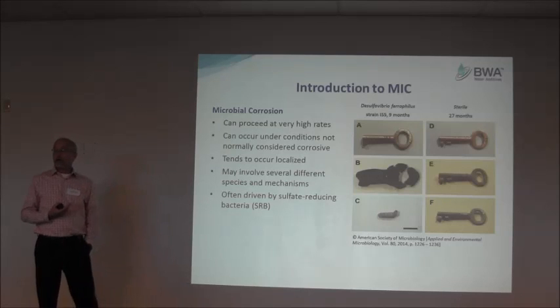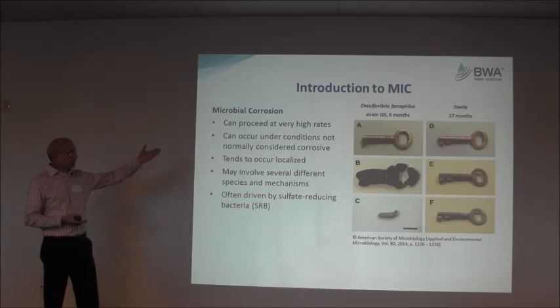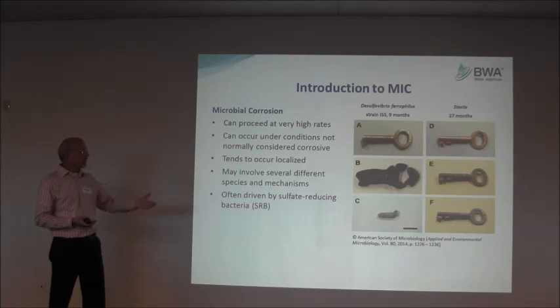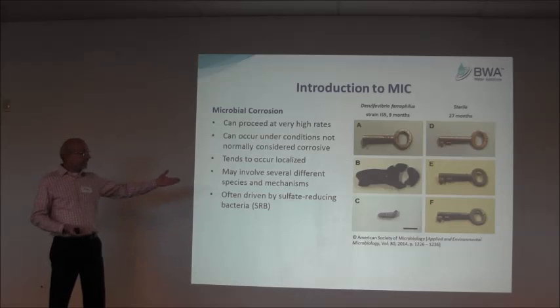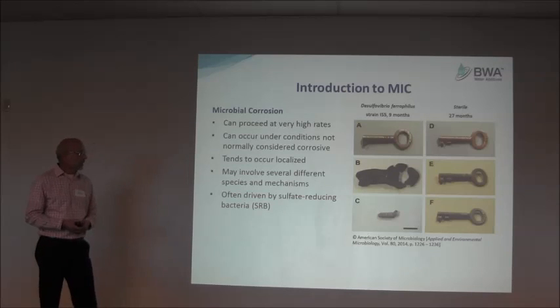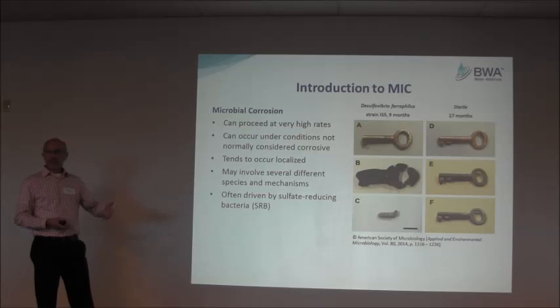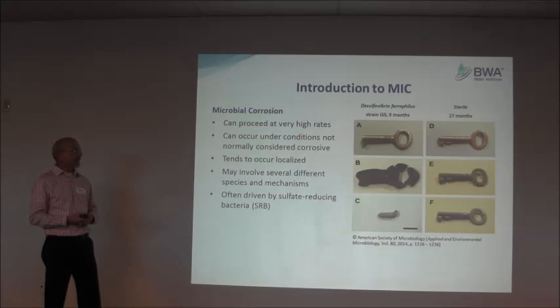Here's what happens in a very short period of time when you introduce sulfate-reducing bacteria to the mixture. A and D are the same type of key at the initial point. B is after nine months in the presence of sulfate-reducing bacteria. C is what's left of the key after nine months once the corrosion products were removed chemically. There's definitely a correlation between sulfate-reducing bacteria and accelerated corrosion under conditions that normally wouldn't be corrosive — anaerobic conditions.